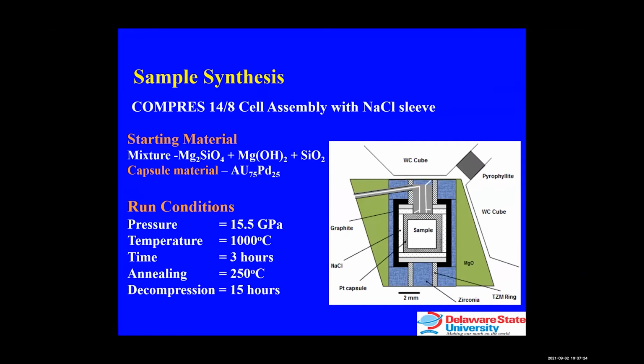So this is the cell assembly that we developed for hot pressing materials for ultrasonic specimens. The critical component of the cell assembly, this is actually a COMPRES 14/8 standard cell. The critical modification that we made to the cell was to replace the MgO insulating sleeve around the sample with sodium chloride. And during the development of the cell, we actually showed that when you hot press material inside an MgO sleeve, it took on an hourglass shape and easily cracked on decompression, compared with cylindrical and crack-free specimens hot pressed in the sodium chloride sleeve.